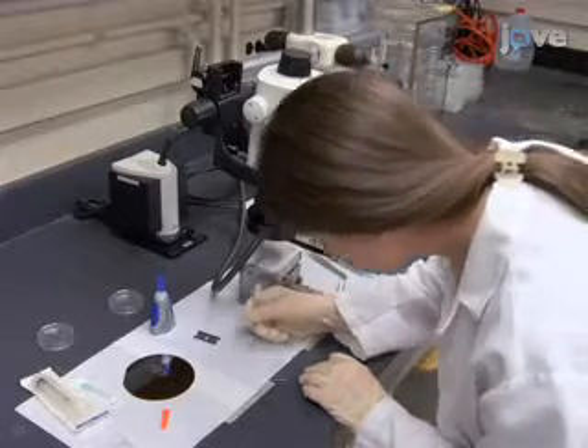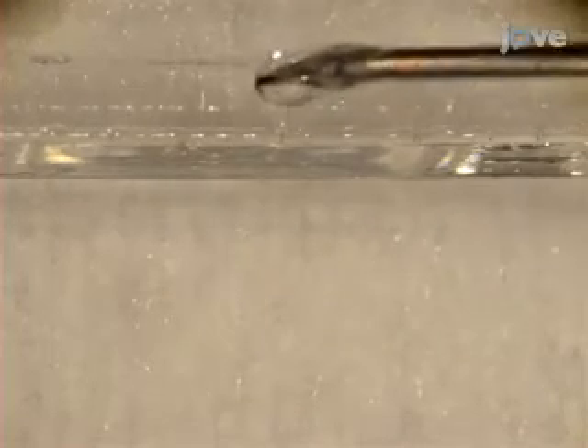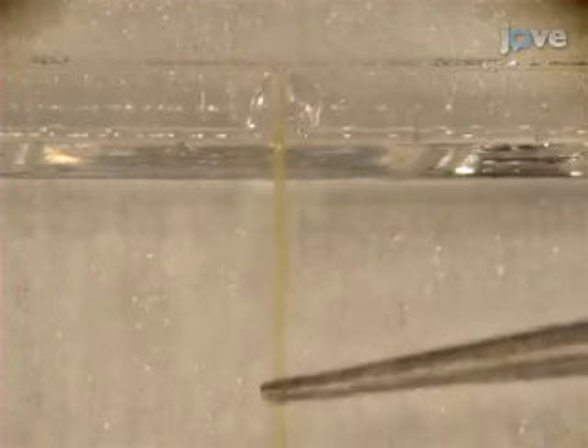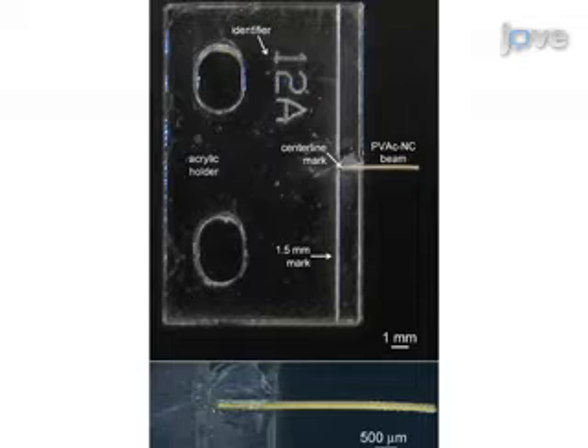Place a small amount of cyanoacrylate gel-based adhesive on the center line of the acrylic holder and carefully adhere a 1.5 mm length of the implant sample to the holder, overlapping the marked center line. Be careful to ensure that the adhesive gel remains only along the 1.5 mm length of the polyvinyl acetate-based nanocomposite being adhered to the acrylic holder.